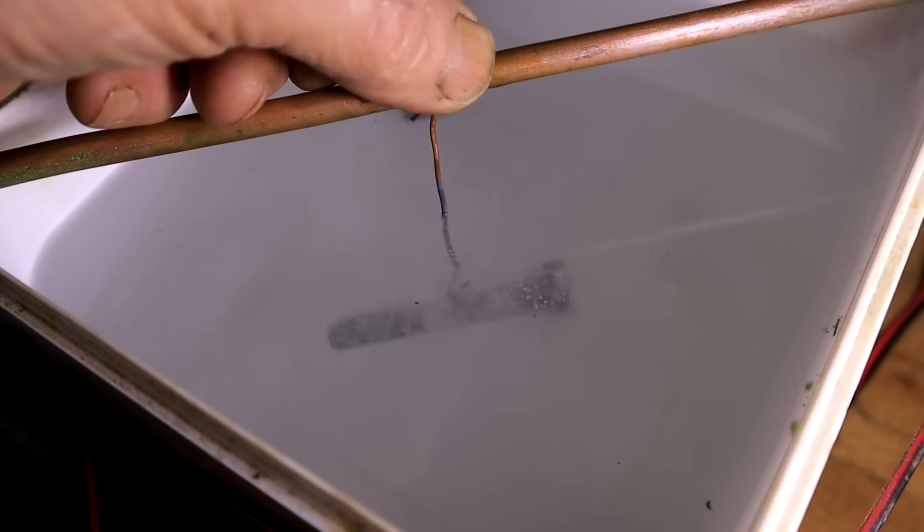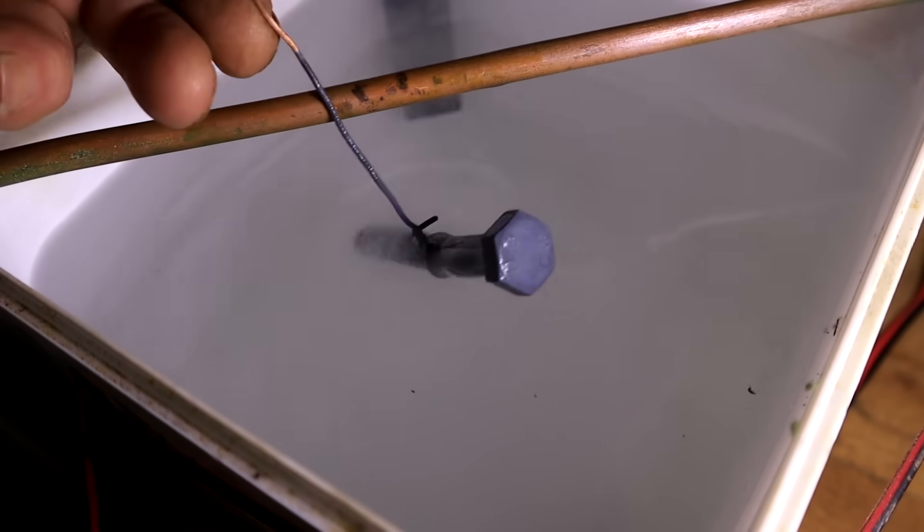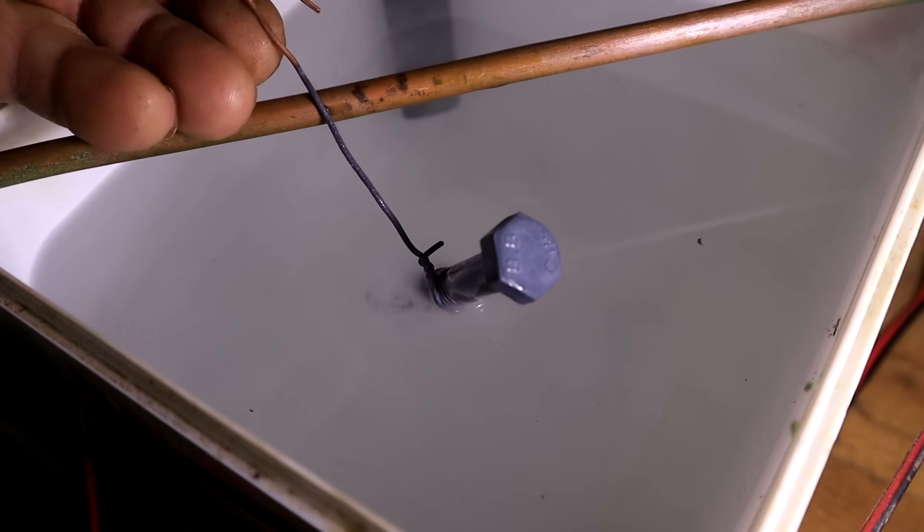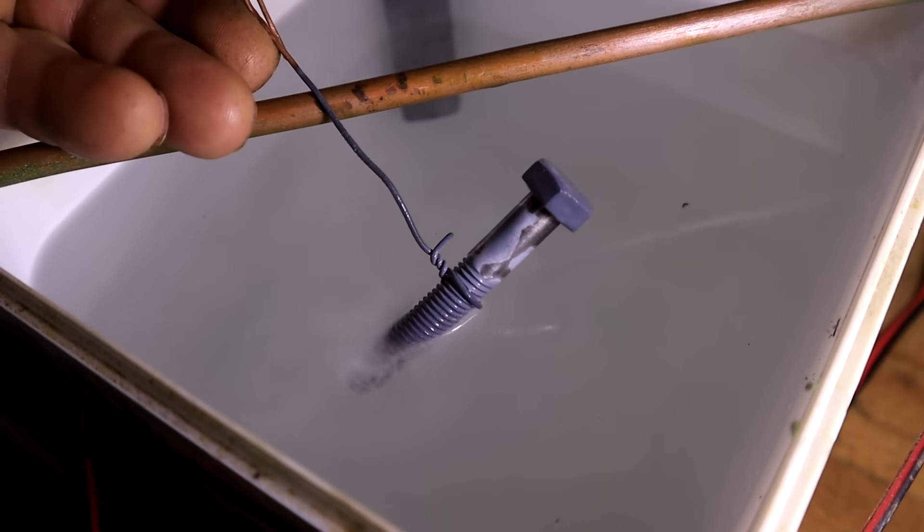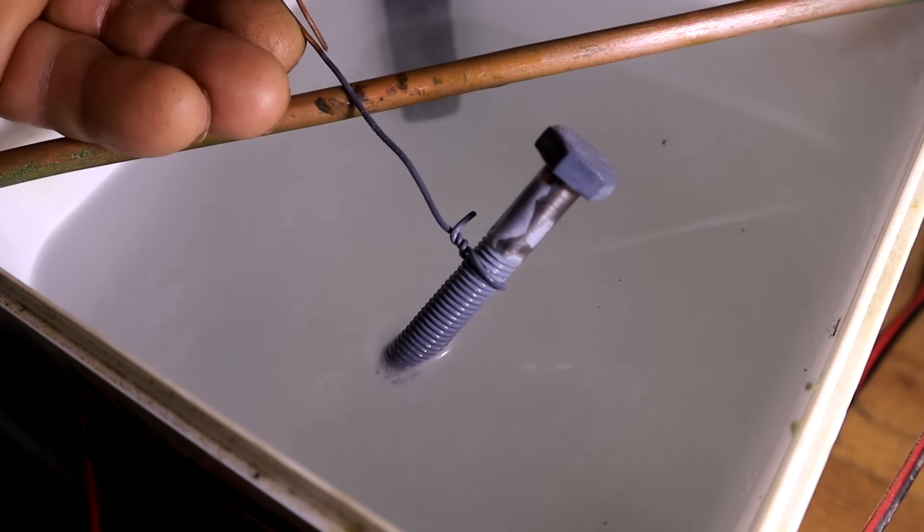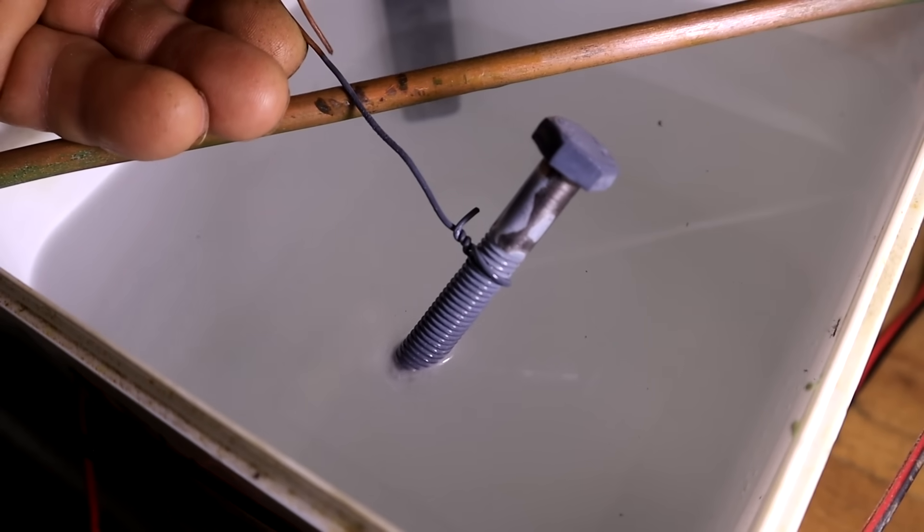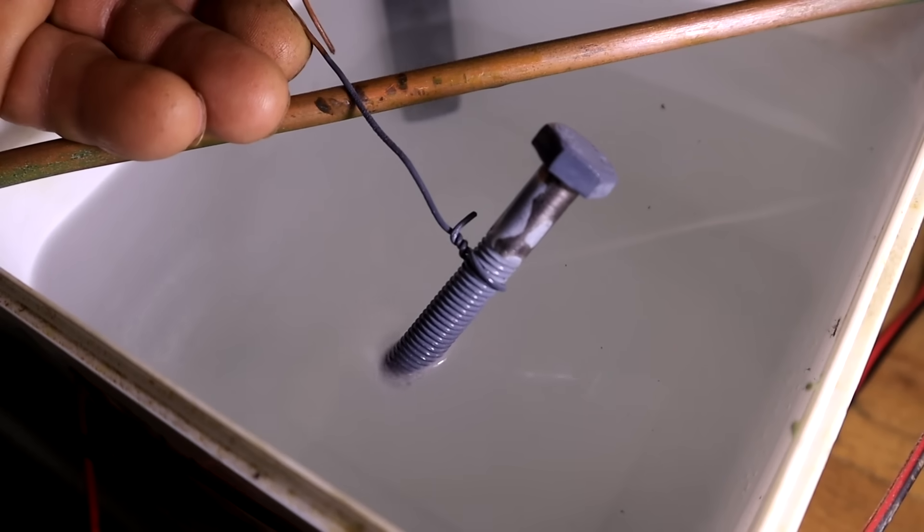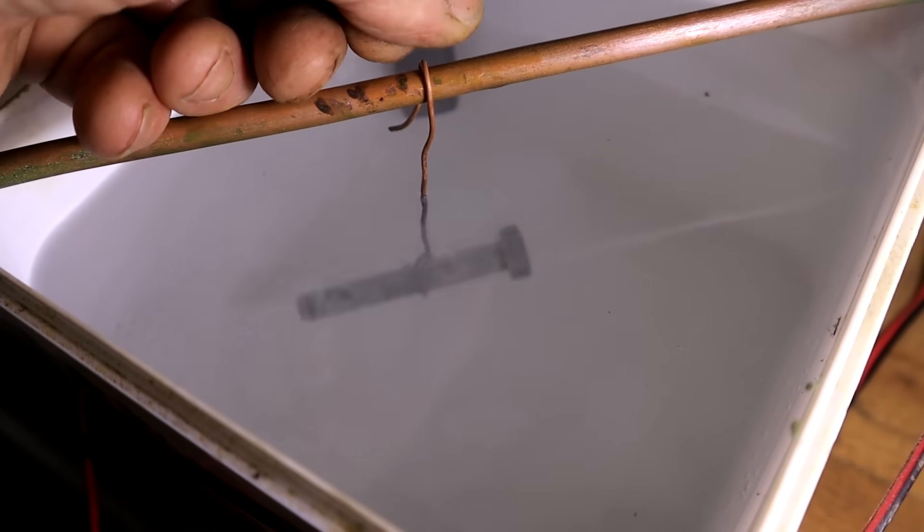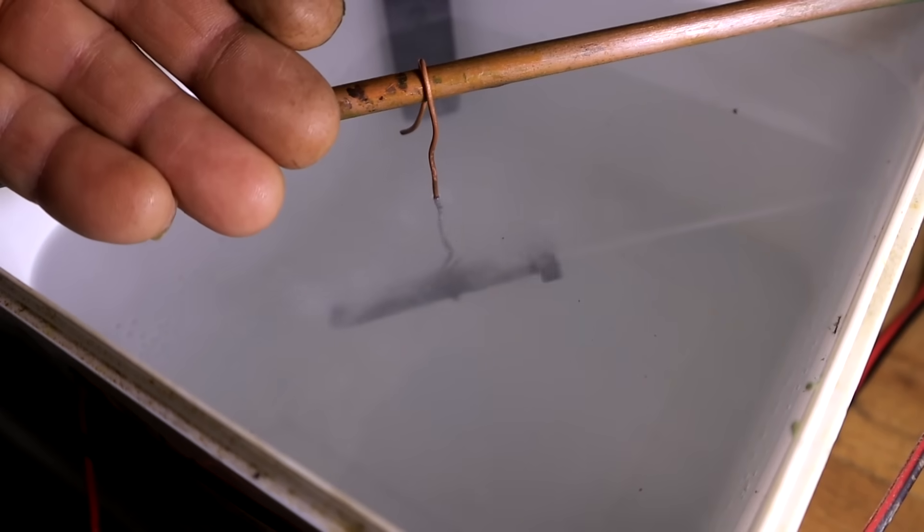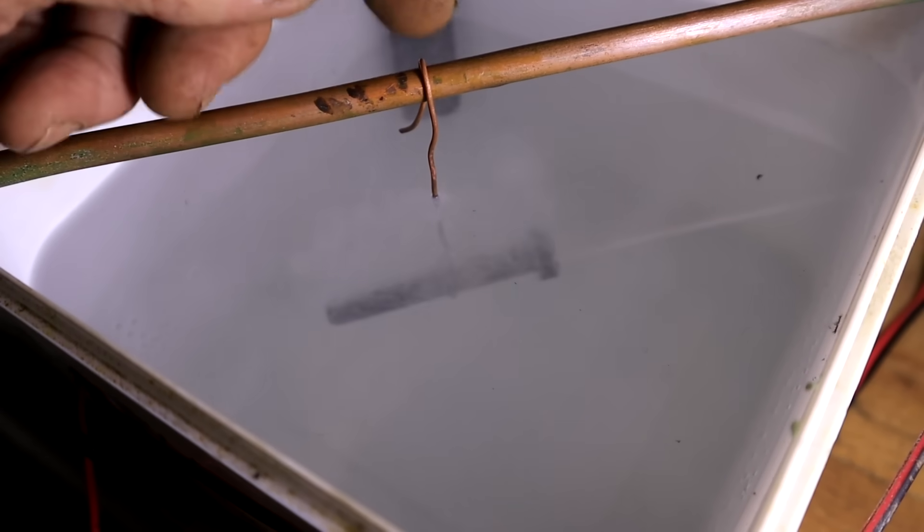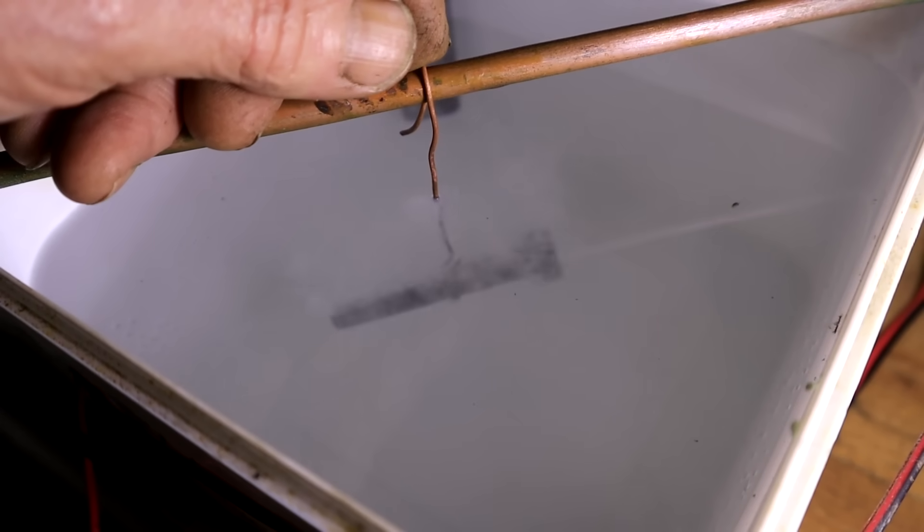Alright, let's take it out. See what we got. Aha! Can you see that gray tone color? That's zinc plating. And look at that. Good example this one. Can you see how I did not plate in certain areas? Now that is most of the time due to improper cleaning. But I've also found that if I put the air pump in here and agitate the water, you get better plating. We can also try leaving it in a solution for a longer period of time.